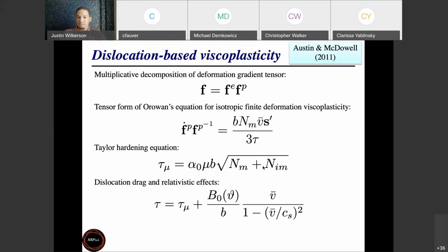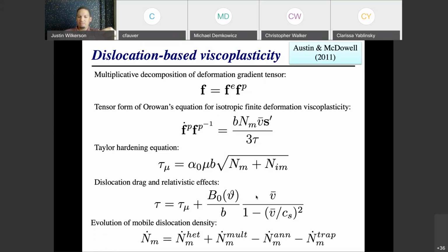And then this is where we bring in the kinetics law for the rate at which dislocations propagate, according to this relativistic equation. And then finally, we need to have an evolution equation for how the dislocation density evolves with deformation. So we account for several mechanisms of dislocation density evolution. You can have nucleation of new dislocation segments. You can have multiplication of dislocation segments. You can have 2 opposite signed dislocations come and annihilate one another. And then you can have trapping as well, where a mobile dislocation will run up against an obstacle where it'll get stopped and become immobilized. So then it moves to the immobile population.